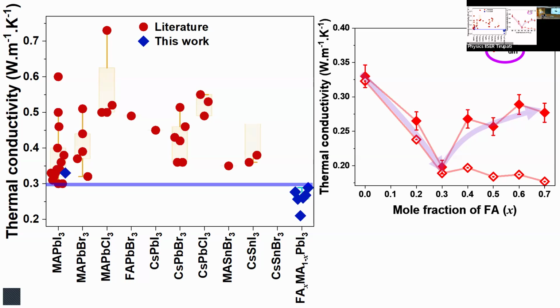It's only MA that scatters very well, but in the beginning, somehow, the presence of FA makes the phonon scattering improve. There's a huge amount of work that you have done over many years with small angle neutron scattering, etc. There's some very peculiar thing there. As you're doping FA, first of all, why is FA not able to scatter so much? The diffusive limit is here, but the actual value is up there.